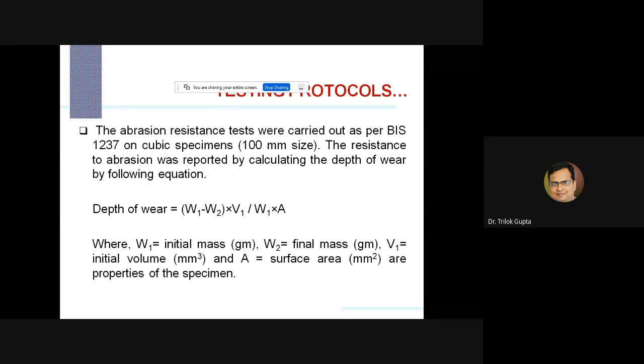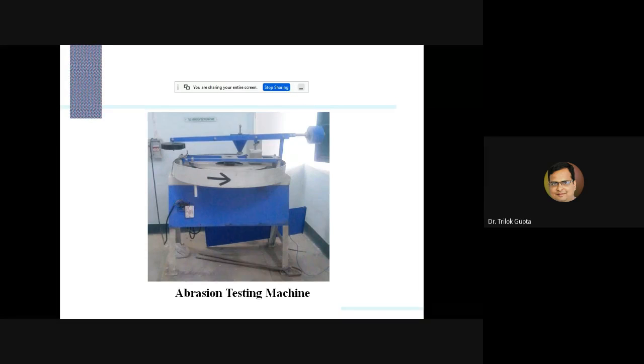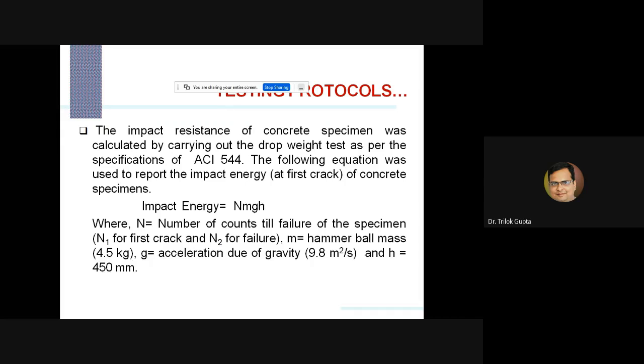Next, we calculate the abrasion resistance in terms of the depth of wear as per IS 1237. The size of the cubes was 100 mm, and the depth of wear as per IS 1237 was based on the difference of the weight loss. We can say that it is initial mass minus final mass, into the initial volume, divided by the initial mass into the area. After that, we find the depth of wear in mm. So that is basically the abrasion testing machine that was used to calculate the abrasion resistance.